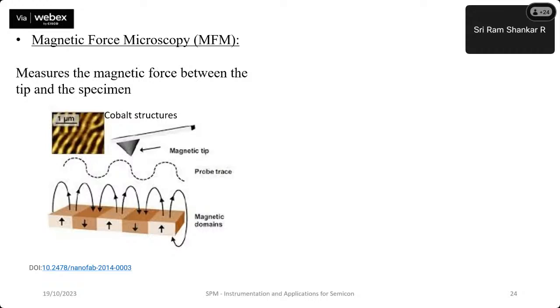In magnetic force microscopy you have this AFM tip, but the tip is coated with a magnetic material. Imagine that your sample is magnetic, but the magnets are all of different orientation, either north and south and so on. Firstly you need to know what is the topography of such a sample. Once you know the topography, then you bring the tip close to the magnetic material, and based on the changes in this magnetic force you can infer whether it is of the same polarity or a different polarity and so on. With this you can characterize the grain boundaries in ferromagnetic materials and so on.